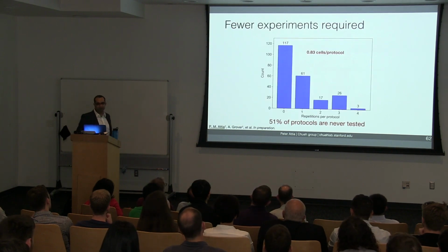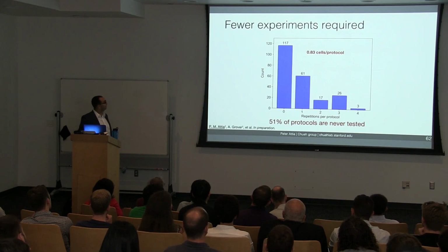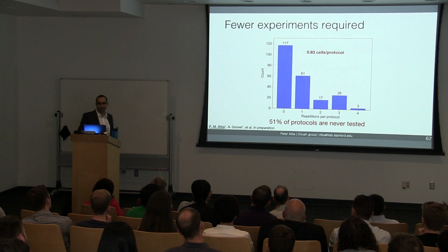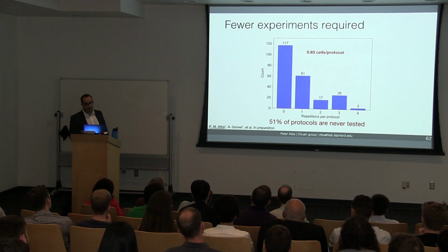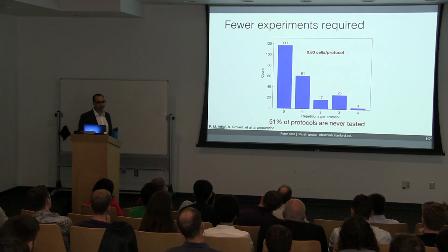This plot shows that we can dramatically reduce the total number of experiments required. Again, on average, we use less than 1 cell per protocol. The way we do this is by using all the data to update estimates for all of the protocols. We also never test the majority of protocols, and only a small subset are tested multiple times. Because again, we're spending most of our resources testing only the most promising protocols.